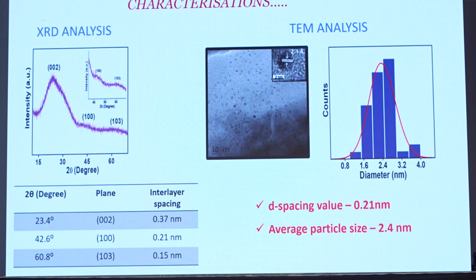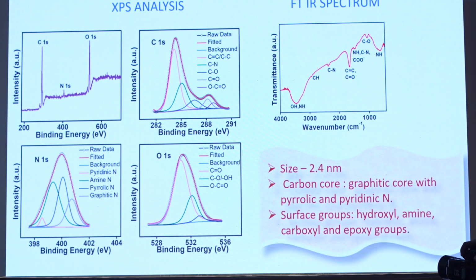spacing for graphitic carbon. And TEM analysis shows that it has lattice fringes with a d-spacing value 0.21 nanometer, which is corresponding to the 100 plane, as we can see from the XRD analysis. Move on to the XPS analysis.